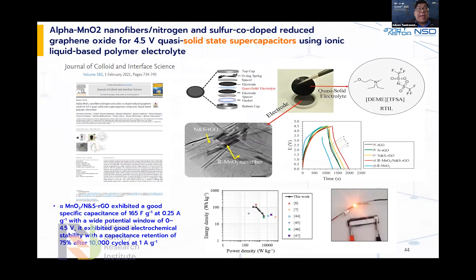We also focus on the high energy density supercapacitor using an ionic electrolyte system to increase the operating voltage of the supercapacitor up to 4.5 volts, which is one of the largest voltages ever achieved in a supercapacitor. With 4.5 volts, we can achieve energy density of more than 100 watt-hour per kilogram, and specific capacitance of more than 165 farad per gram.